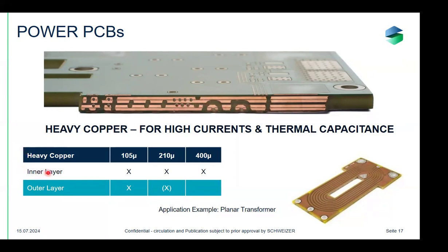So what we typically do is that we focus on the inner layers for the heavy copper. So 105 microns, it's where we start with heavy copper layers, but it can be up to 400 microns. On the outer layers, what you see here is a 6-layer construction. On the outer layers, we typically stay with a maximum of 105 microns, because typically in the outer layers, you want also to assemble some components, and therefore you have to have a finer etching pattern, which is not possible with heavy copper. And you also want to have a good coverage of the solder mask, which is also a challenge if the copper thickness increases too much in the outside.